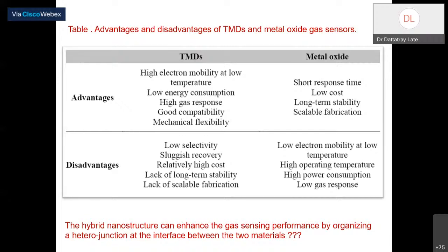So here my mobility is slightly low, and for temperature, I'm working here with room temperature. In traditional metal oxide, I find the response time is short. Here the response is slightly more in my material, and there is low energy consumption, because metal oxide functions only at high temperature. Here my sensor is functioning at room temperature, so that is a very important parameter. And the mechanical flexibility is very good in this transition metal dichalcogenide.